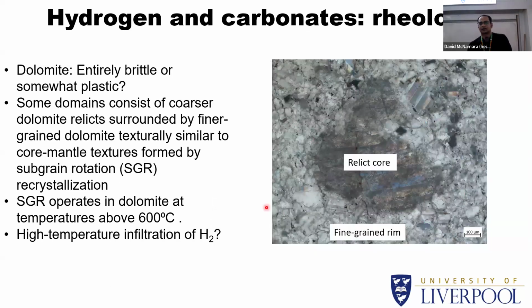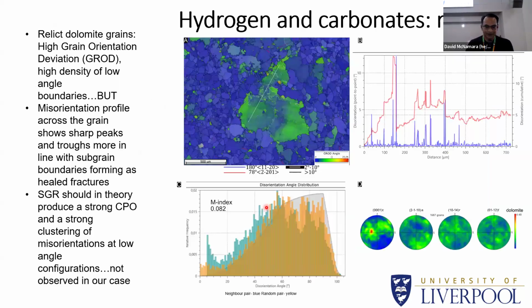So the first bit, dolomite deformation: is it entirely brittle, or is there a component of recrystallization? If we look at the fine-grained domains of dolomite that I described previously, you have textures that resemble subgrain rotation. You've got these larger relict cores with a finer grained fringe of dolomite. And such textures, if they were to form by recrystallization, you'd need temperatures of above 600 degrees Celsius. So we got EBSD scans from this domain. And if you take a cursory look at it, it seems that it could have recrystallized.